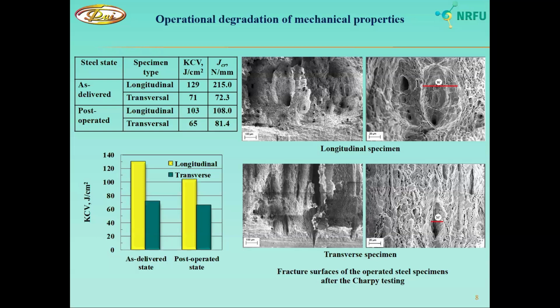Analyzing fracture surfaces for the operated steel specimens after Charpy testing, we can see surface texture depending on the specimen orientation relative to the pipe axis, and it's mainly associated with delaminations, more pronounced for the transverse specimen. And also we can see that the width of delaminations, characterizing residual opening of the defect under fracture, is smaller for the transverse specimen, indicating a lower brittle fracture resistance.